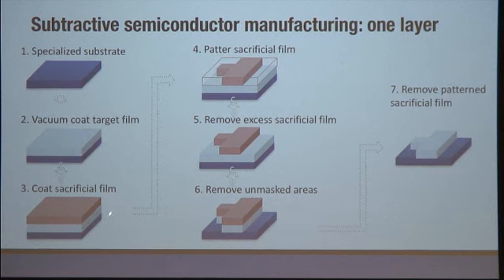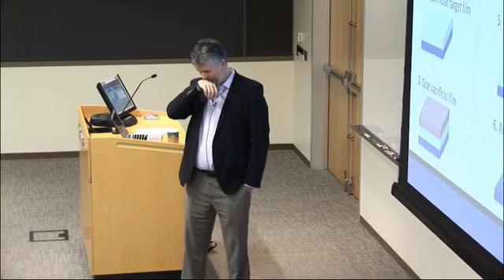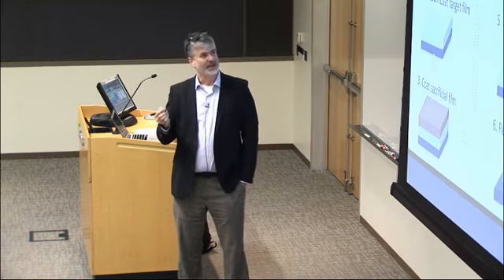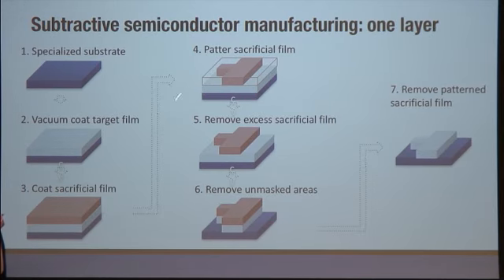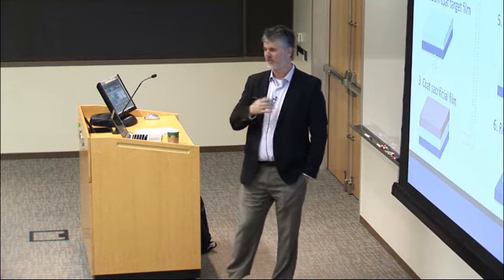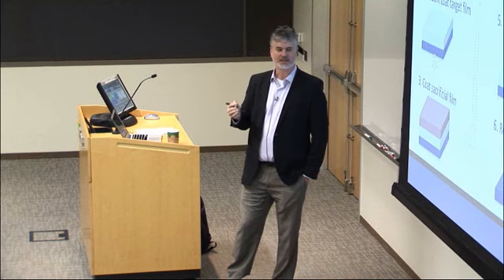You coat it with various highly engineered polymer, very expensive and usually environmentally unsound photoresists, photoacids and other things. And you pattern that with UV light. You throw away most of that. Then you use that to etch in yet another kind of toxic effluent etching process. And then you throw away that mask completely and you end up with your final feature, where you've gone through 3 steps of constant removal and disposal of material to get to your final target.